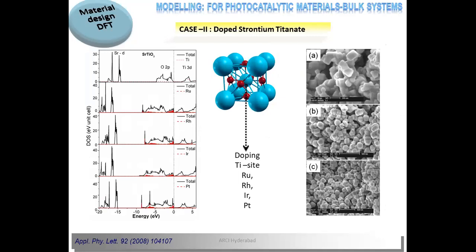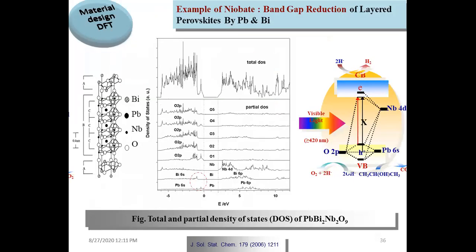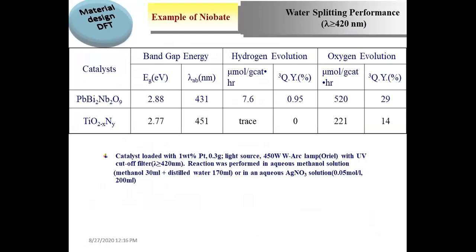Same thing we did for the second case of strontium titanate. Let us not worry about that. And similar things I have for lead bismuth niobate, where we made use of electronic structure calculation to interpret the high efficiency of the lead bismuth niobate photocatalyst, which works very well in visible light. So these are the different systems we worked on and published. But then ultimately this tabulation tells you about titanium oxynitride, where I was telling you that you can tune the absorption property of TiO2 by doping of, let us say, nitrogen. It is compared with lead bismuth niobate.